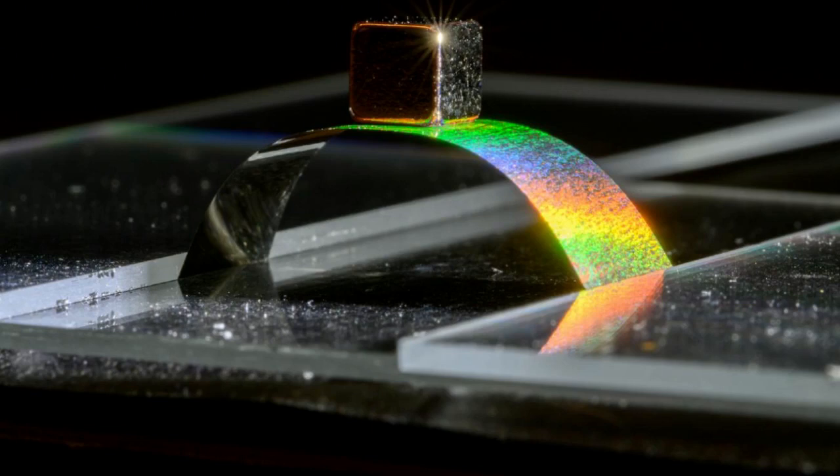The researchers say that these cracks are very difficult to prevent in the structures they are trying to build, so they developed a new strategy that allows them to self-assemble the particles while keeping the template wet. This prevents the films from cracking. But because the particles are wet, they have to lock them in place using electrostatic forces so that they can fill them with metal.